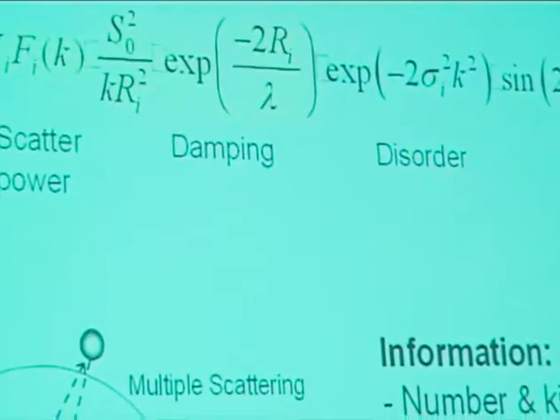So in that sense, it is not as good as X-ray diffraction. On the other hand, it is for certain materials better than X-ray diffraction because you don't need long distance coherence. You don't need single crystals because you only need a well-defined surrounding of this atom here. So on a local scale, you must have structure. And if you have that, you can use this technique to determine that structure. For that particular reason, it is so important for catalysis. Because in catalysis, we often have very small catalyst particles, which are too small to be seen in XRD. And then you may still be able to see them in EXAFS and determine the structures surrounding each atom.